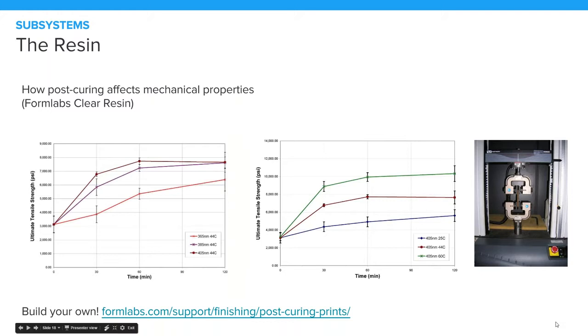You can see the testing rig on the right side. Basically, you take a small sample and you pull it until it pulls itself apart. You can see the chart on the left is showing different laser frequencies at the same temperature, while the chart on the right is showing the same laser frequency at different temperatures. You can see that with a 405 nanometer wavelength UV light and 60 degrees Celsius, you get a huge increase in part strength. This is really critical for functional components like tough resin or castable resin and stuff like that.